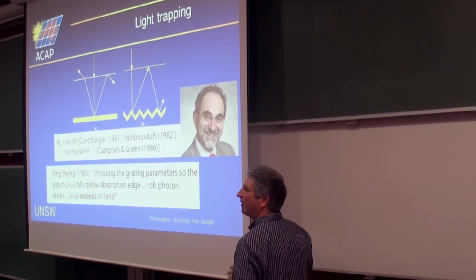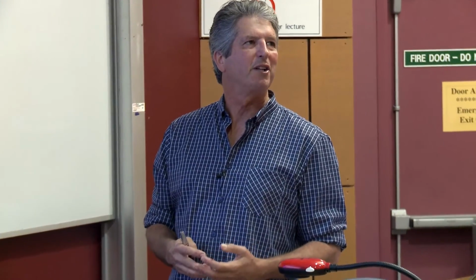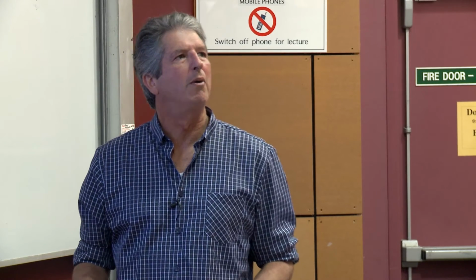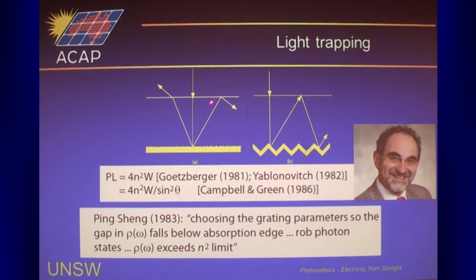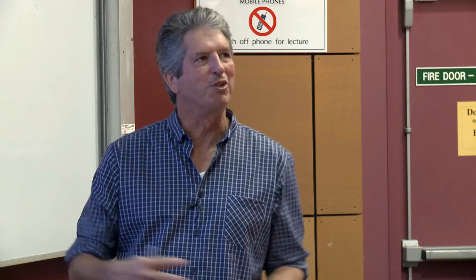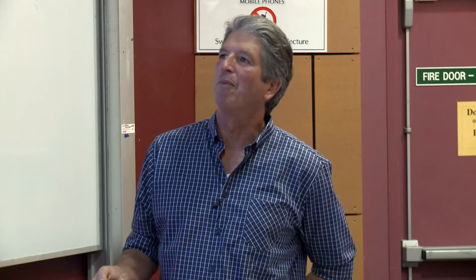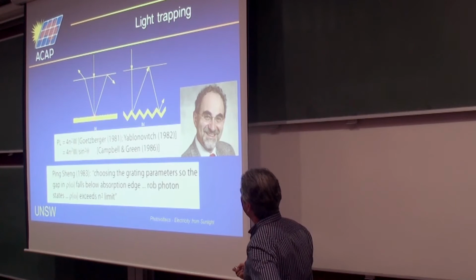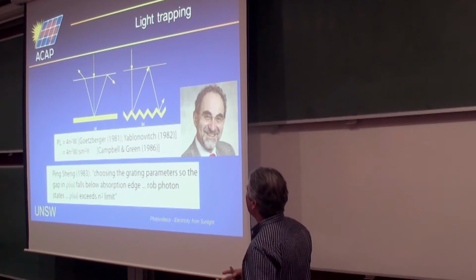So as I said, n is very high. The refractive index for silicon is 3.5. So if you figure out 4n squared, you get something like 50. So by doing something like this, you can increase the path length 50 times over that of a single pass across that layer. So that's quite an important boost. If you've got a solar cell that's 300 microns thick and you multiply that by 50, it's something like 1.5 centimeters. That's sort of the absorption depth that you're working with. So it's really quite a substantial improvement in terms of trapping light within the device.